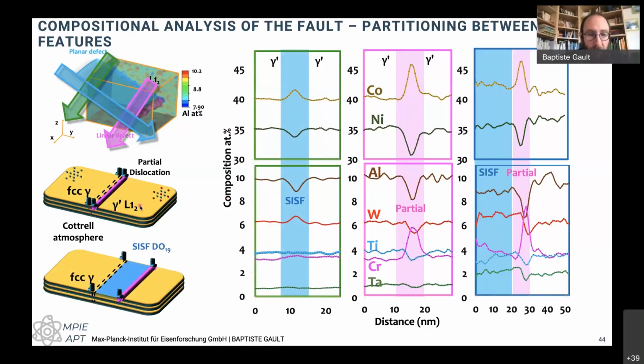But then we can also look ahead, along this planar defect, right ahead of this partial. What we see is that there is an increase in the aluminium, as if it was being pushed by the moving dislocation. And we can see that there is a depletion of tungsten right ahead and a segregation of tungsten on the fault. And this we interpreted as the tungsten from in front of the fault being sucked in by the partial dislocation and then positioned onto the stacking fault itself, where actually it makes sense because this DO19 structure is very close to Co3W.